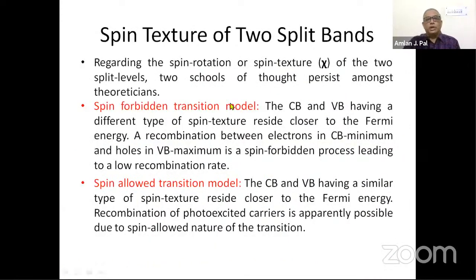That's the spin forbidden transition model. It is said that the conduction band and valence band, having different types of spin textures, reside closer to the Fermi energy. Because I said that the conduction band and the valence band are now spin split. Now, what is the spin state of these two? Because finally, electrons will reside at the lower of the two conduction bands, and the holes will reside at the higher of the two valence bands. So it is now important to know what is the spin texture of this conduction band and of this valence band.